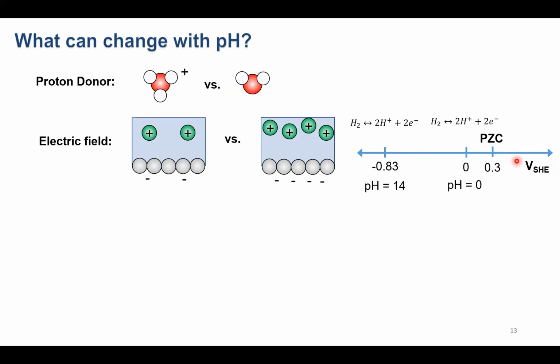the scale. And so what this means is, if we carry out hydrogen evolution or hydrogen oxidation in an acid electrolyte, we're much closer to the PZC than we are if we carry out those same reactions in an alkaline electrolyte. How far we are from the PZC determines the magnitude of our electric field. And so if we go from acid to base, we're going to have a much larger electric field and also a much higher concentration, in this case, of cations close to our electrode surface.